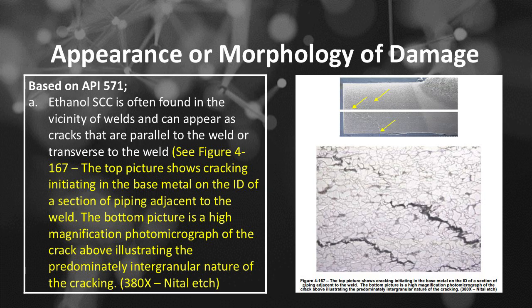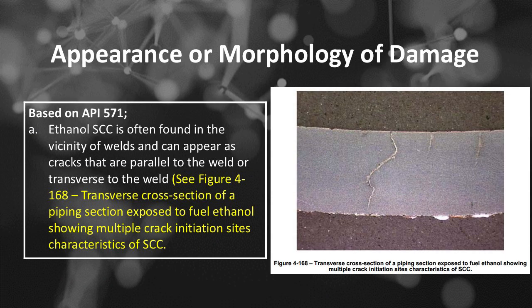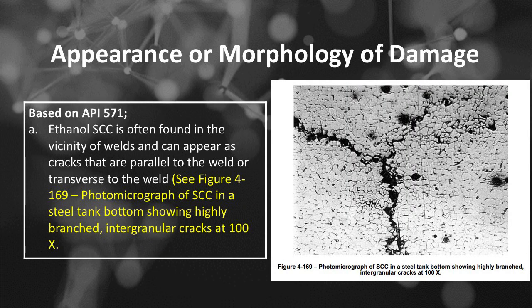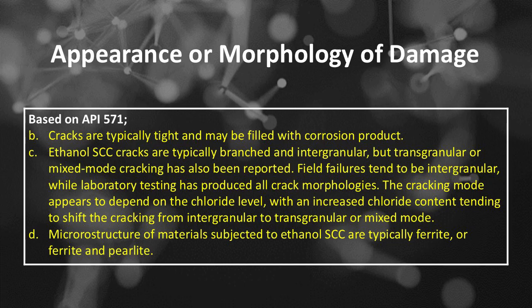See Figure 4-167, the top picture shows cracking initiating in the base metal on the ID of a section of piping adjacent to the weld. The bottom picture is a high magnification photomicrograph of the crack above illustrating the predominantly intergranular nature of the cracking, 380x, nital etch. See Figure 4-168, transverse cross-section of a piping section exposed to fuel ethanol showing multiple crack initiation sites characteristic of SCC. See Figure 4-169, photomicrograph of SCC in a steel tank bottom showing highly branched, intergranular cracks at 100x. Number B, cracks are typically tight and may be filled with corrosion product.